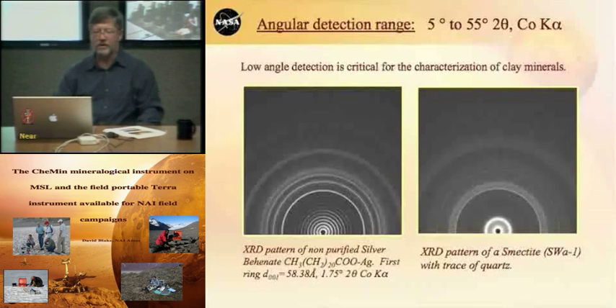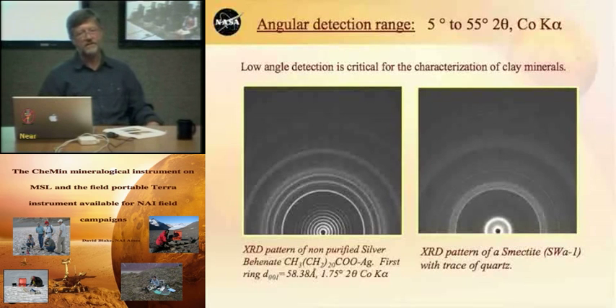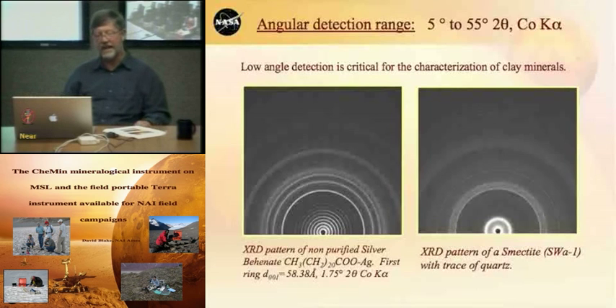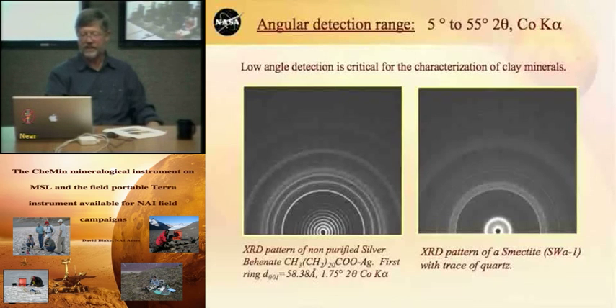So now that we know the geometry, it's a transmission geometry, we have to worry about the details of where we want to look: what 2 theta angles, what range, what resolution. We know that we would like to see in the low 2 theta regions because we want to see clays, and that's where the principal peaks of clays are located. Here's an XRD pattern of smectite, and you can see this is the principal peak of smectite, and that's located down around 5 or 6 degrees 2 theta. So we want to have an angular range that will encompass clays. We also want to go out far enough to encompass other minerals of interest.